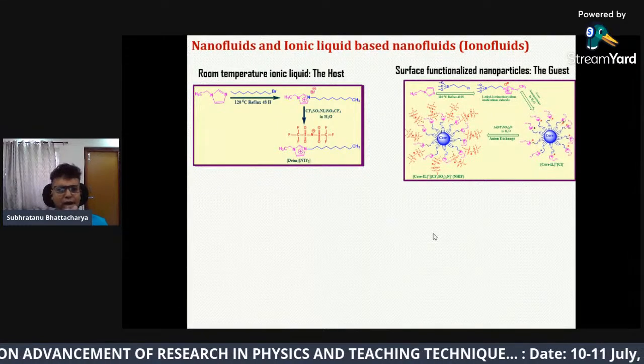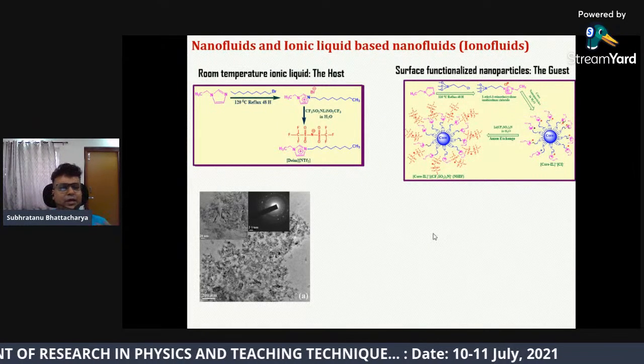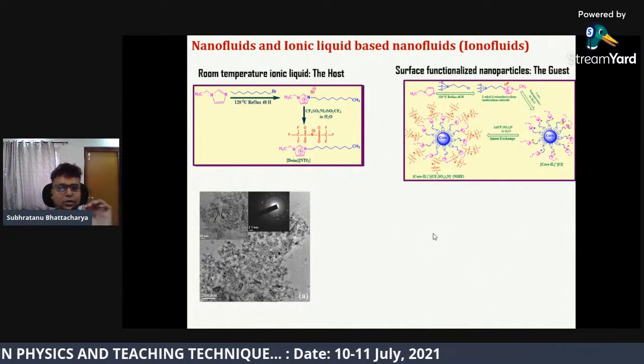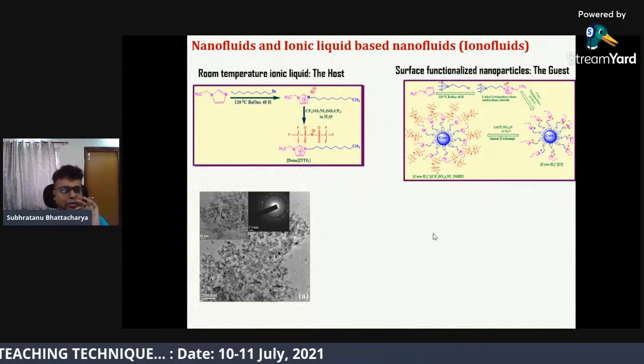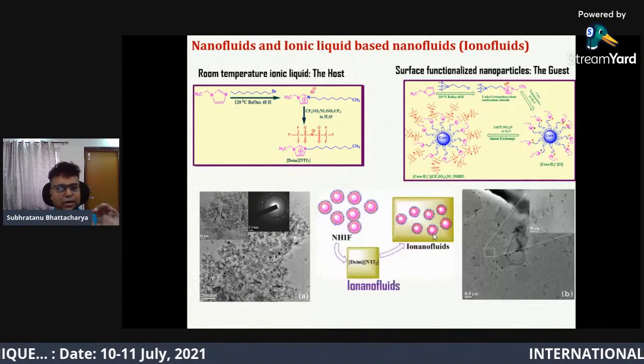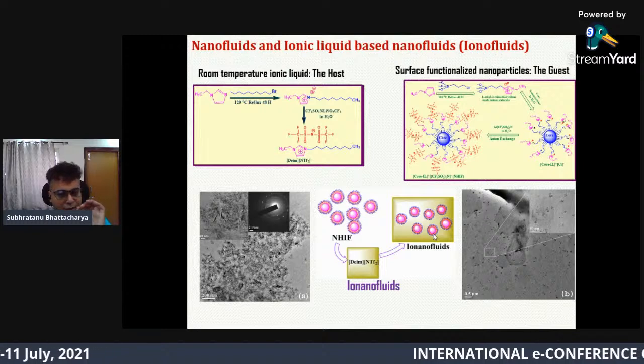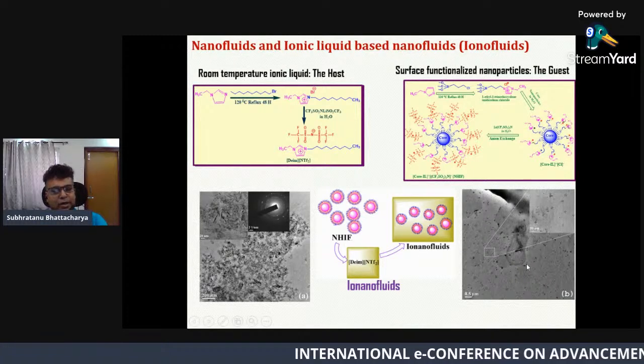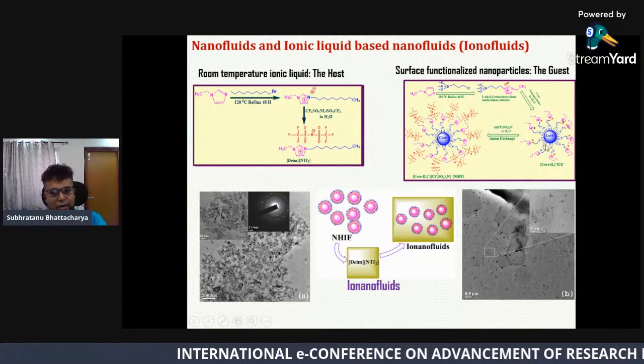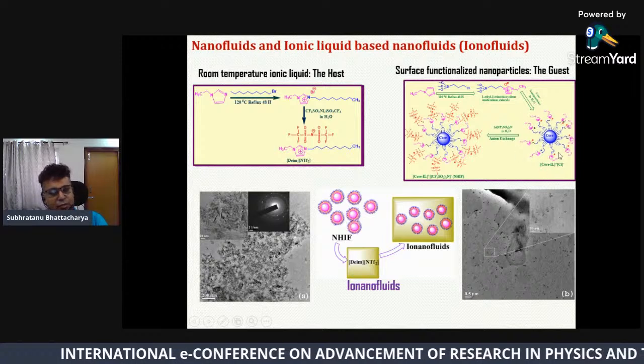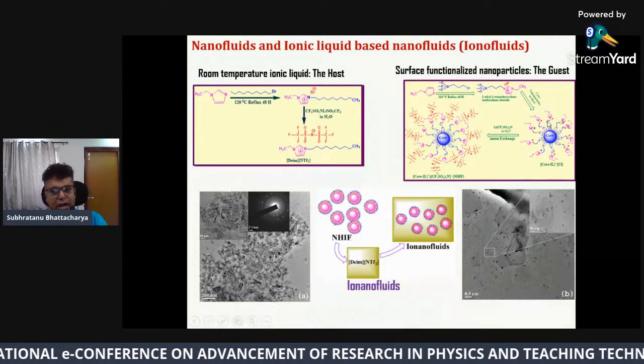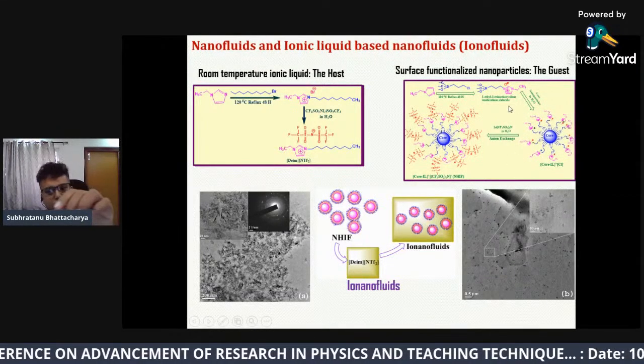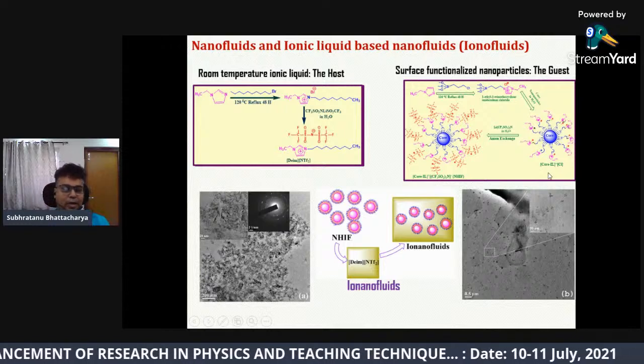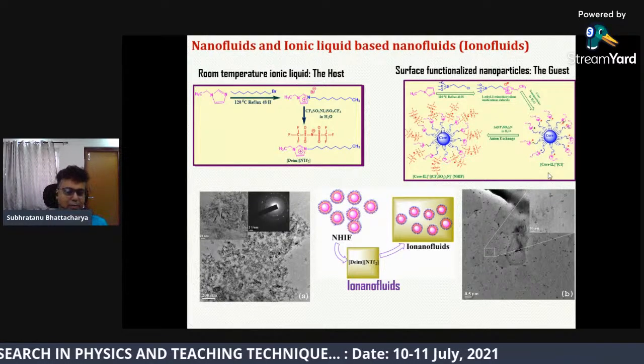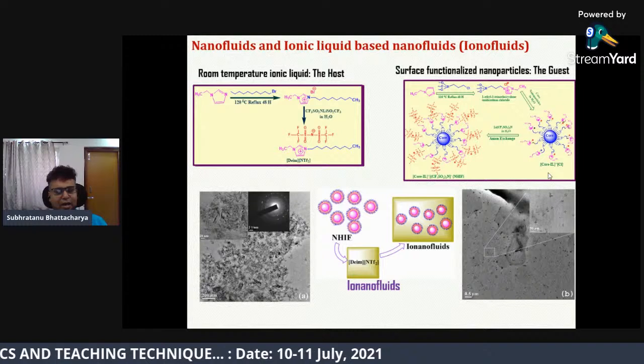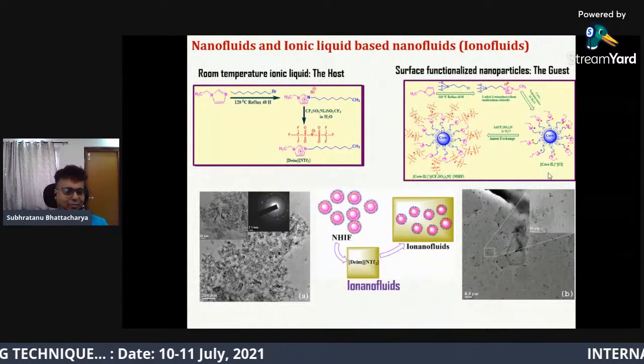So what we have done, we actually removed the crystallinity of the ionic liquid. We were able to do that by incorporating some nanoparticles. These are surface modified nanoparticles, surface modified by ionic liquid species, and then incorporating these into the ionic liquid. That happened by accident. We were just trying to get something else.